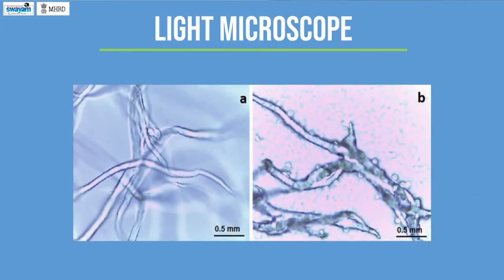Light microscopes can be used to study swelling changes of native fibers as well as morphological changes of refined cellulose fibers which are subjected to physical, chemical and biological pretreatments of wheat straw and corn stover. These are optical images of microfibers taken before and after pretreatment of cellulose fibers. By looking at these images, we conclude that the fibers are swelling after the pretreatment process.